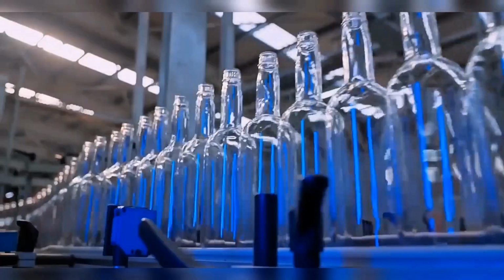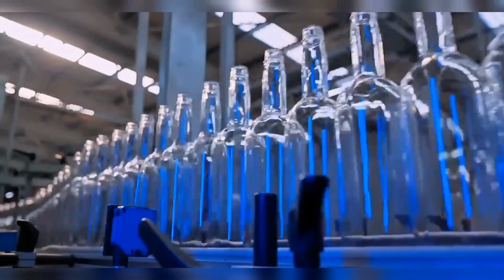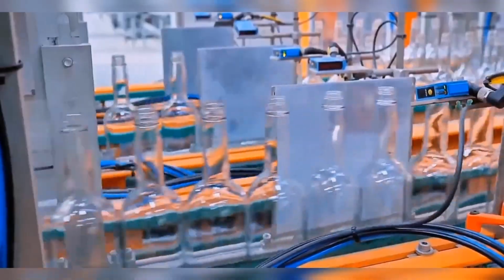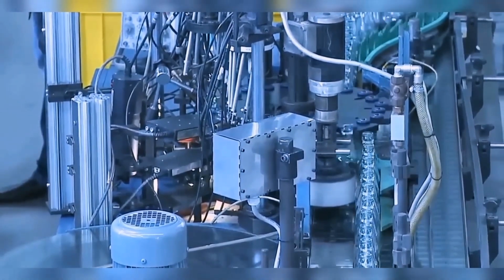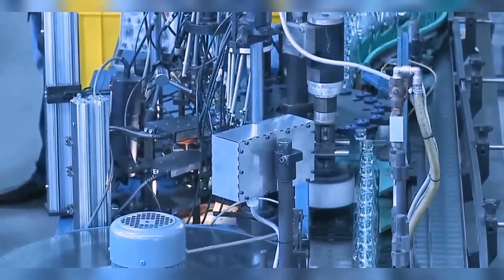Typical container defects and root causes. Common container defects include poor distribution due to thin walls or heavy heels, seams or parting line defects, stones, bubbles, wrinkles, and dimensional failures. Causes range from incorrect gob weight, dirty or overheated molds, improper takeout timing, to contaminants in the batch.